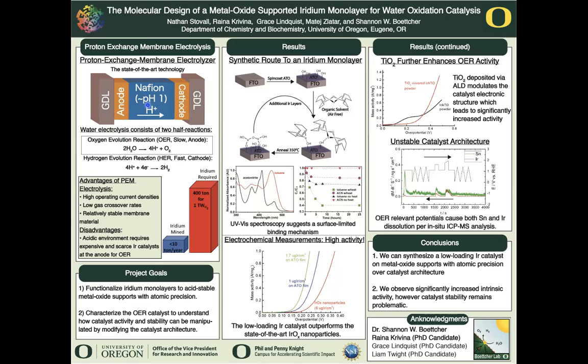But unfortunately, due to the acidic conditions of this Nafion membrane, really only iridium has shown to be an active catalyst that's also stable in the acidic and oxidizing conditions of OER. But unfortunately, as you can see on this bar chart here, if we wanted to get hydrogen on the terawatt scale, we need 400 tons of iridium, which is 40 times the amount of iridium we even mine yearly.